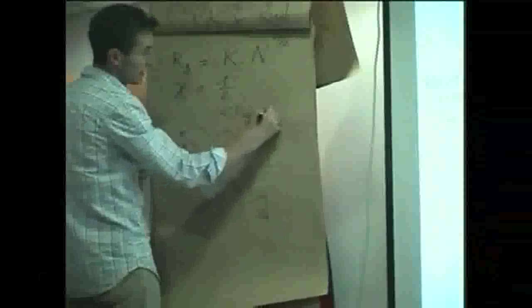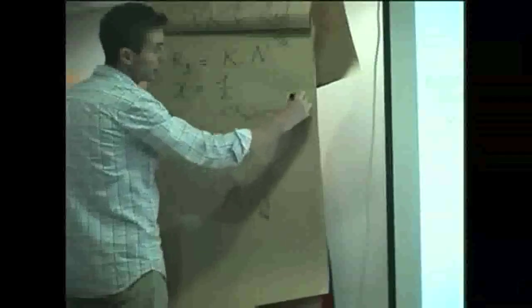So you end up with the average of R0 square equal to N A square. So the average of R0 is equal to A times n to the power 1 half. It means that the size, this length here, R0, the average value of this R0, is equal to A n to the power 1 half.